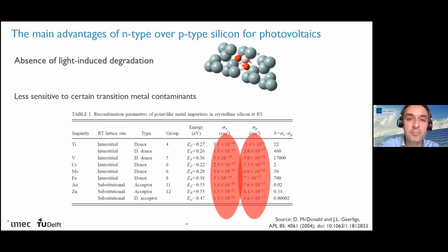But on top of that, typically N-type silicon has much higher minority carrier lifetime, so longer diffusion lengths than P-type. The main reason is that N-type is less sensitive to certain transition metal contaminants. The presence of such contaminants becomes more and more important as you go to higher efficiency devices. If you have a cell efficiency of 20% and a little bit of iron in your cell, it's not such a big problem. But if you have a cell efficiency of 24-25%, the same amount of iron can really kill your device.